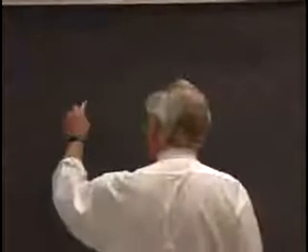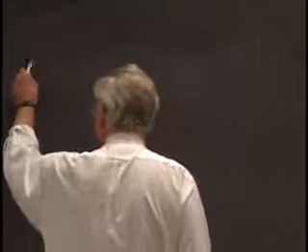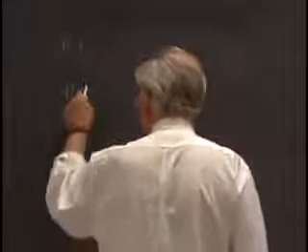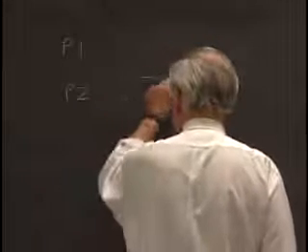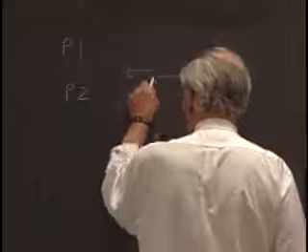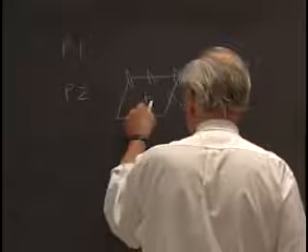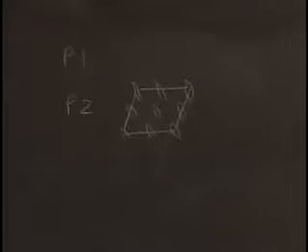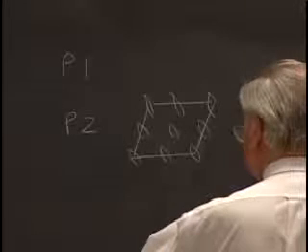We've gone through quite a few of them. I won't bother to draw the pattern of the symmetry elements, but we put no symmetry at all in the general parallelogram net, and that is plane group P1. Maybe I will draw the figures after all. P2 was a two-fold axis dropped into a net which had to have no specialized shape, simply because a two-fold axis requires nothing but a lattice row if one translation is combined with it.